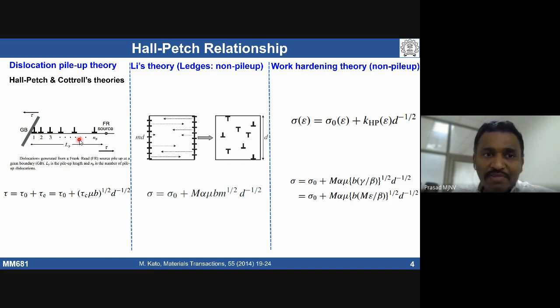The problem with the pile-up theory is that the observations were in steel - all the initial observations are actually on steel. But when they did ultra microscopy, people did not find piling up of dislocations in materials like iron, and also in aluminum, which are high stacking fault materials. We do not see pile-up of dislocations because aluminum is a high stacking fault material, and BCC iron is also a relatively high stacking fault energy material. So people did not observe pile-ups, and that's why people ruled it out - we cannot consider pile-up theory applicable to arrive at the equation which describes how stress depends on grain size of a material.